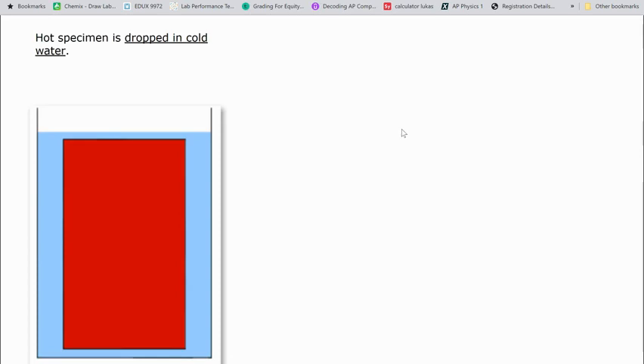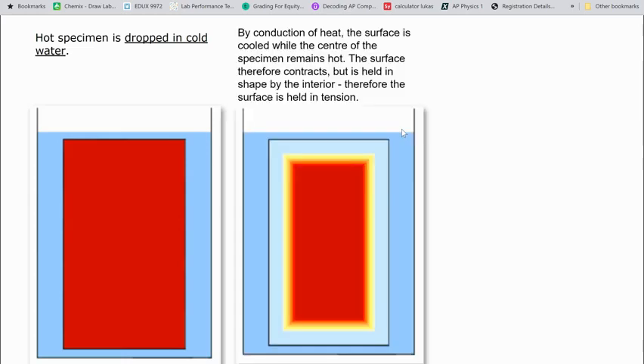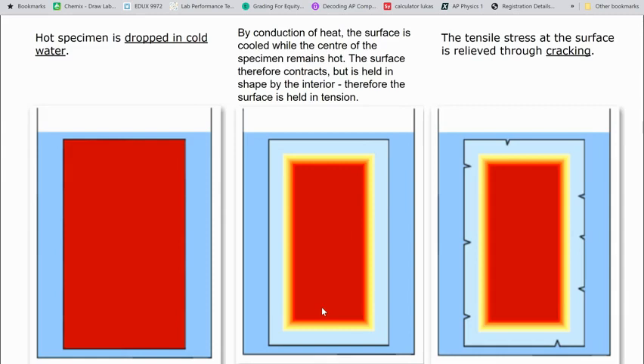So if we look at an example of that, if a hot specimen is dropped into cold water, then the conduction of heat is going to cool the outer material, but because ceramics have a low thermal conductivity, the inner material is going to stay warmer. And therefore, the surface is going to be held in tension. And tensile stress at the surface is relieved through cracking, through the brittle nature of the ceramic.